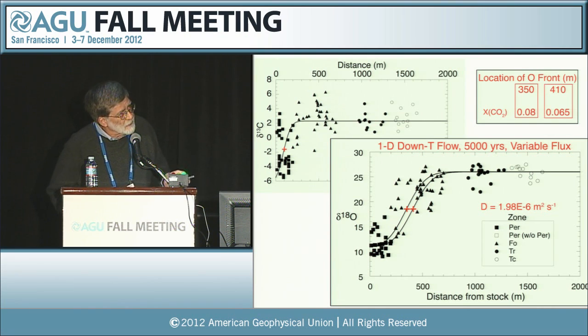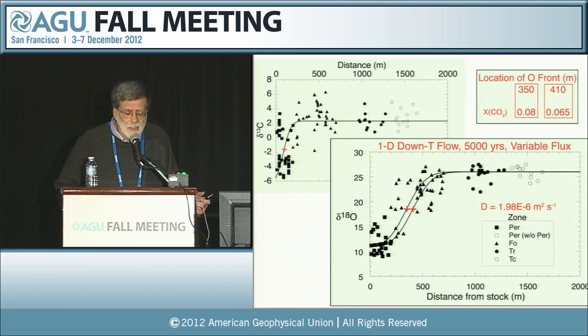Okay, so now these mole fractions are low, and that's consistent then with these fronts being formed by the infiltration of water-rich fluids. These values, however, are a bit higher than what Steve Cook and I estimated for infiltrating fluid based on applications of calcite-dolomite thermometry to the periclase reaction, and those values we estimated to be very, very water-rich, 0.04 or even less. So there are some inconsistencies here.